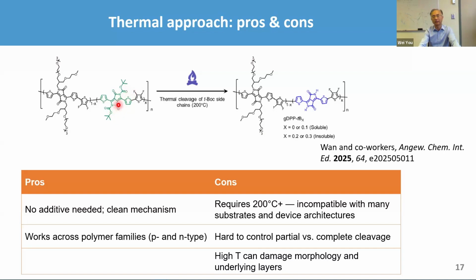This is essentially the DPP, using a similar idea: tertiary ester, heat it up to 200 degrees C, and you end up with this material in theory, and you will end up with insoluble and better performance. So the pros include no additive, you only need the heating. Because this approach is very benign, you can work with many different polymers, P and N type. But the bad news is that you do need a high temperature, 200 degrees C, 250 degrees C in some cases. That would be incompatible with many substrates.